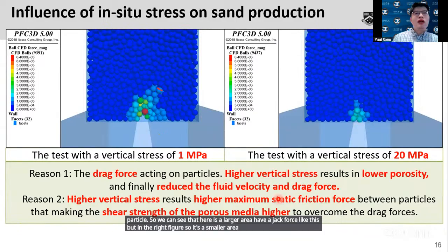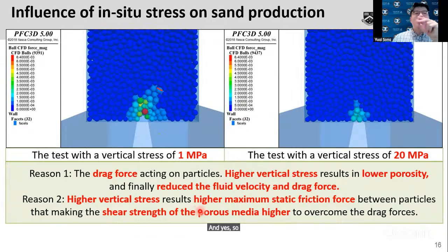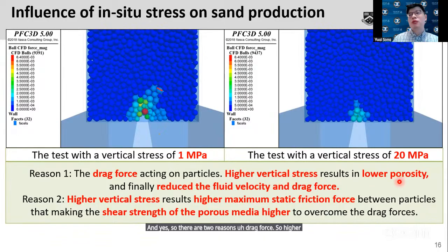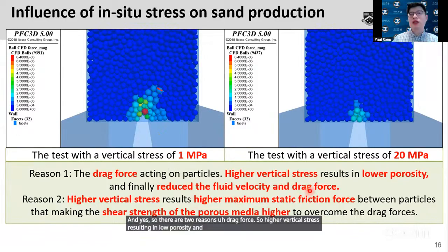There are two reasons. First, for drag force, higher vertical stress results in low porosity and reduced fluid velocity. Second, high vertical stress results in a high maximum static frictional force, which makes the shear strength of the porous media higher, so as to overcome the drag force.